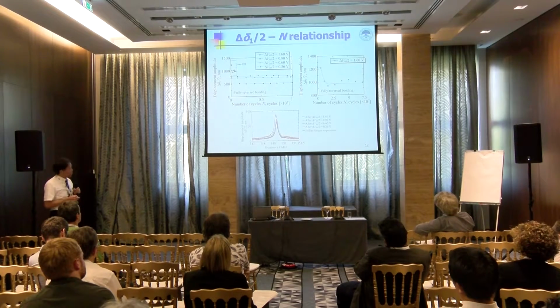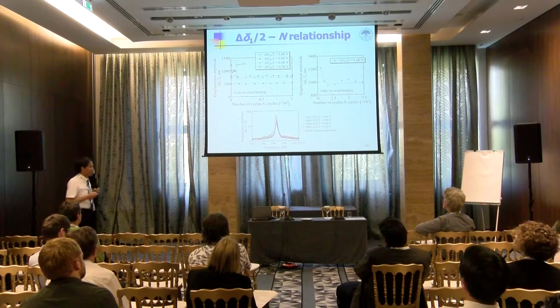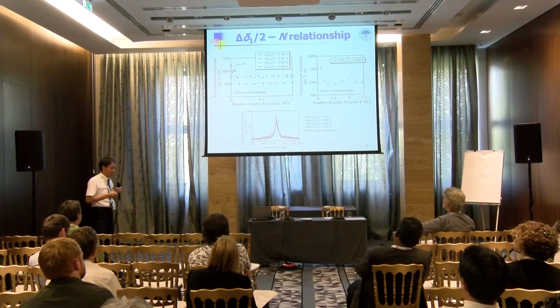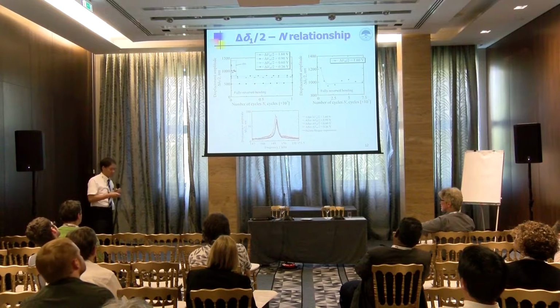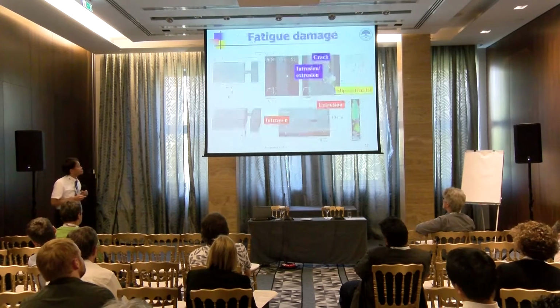And this is a frequency response curve. As you can see, after the input voltage of 1.6 volts, the peak was shifted. So from this fact, we judged that the fatigue damage appeared in the test section. And so we finished the experiment.